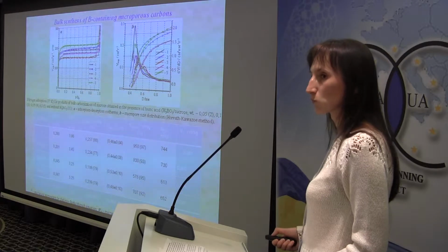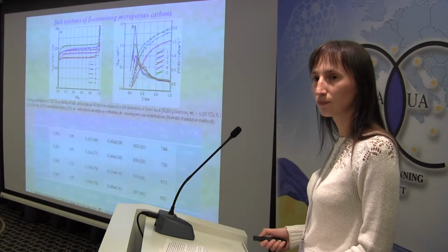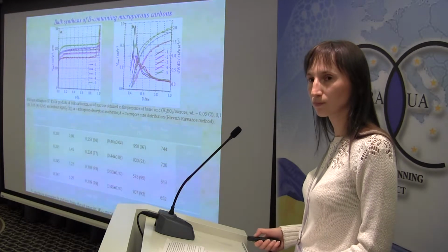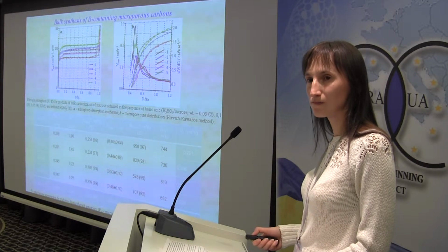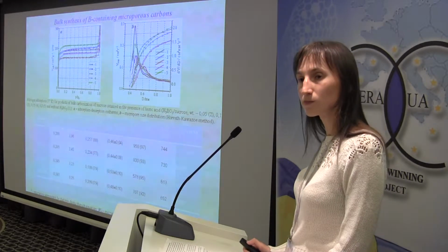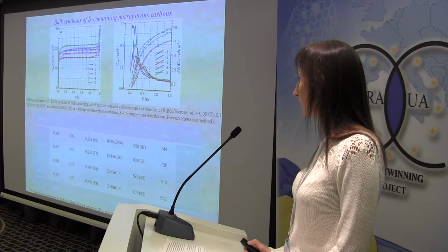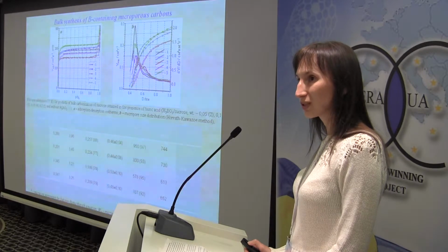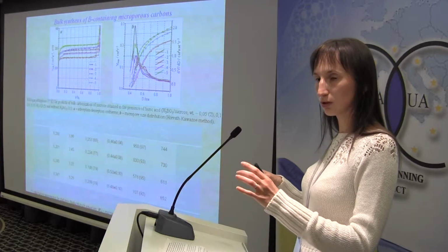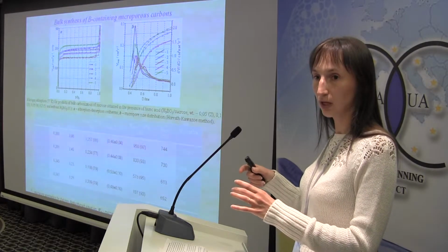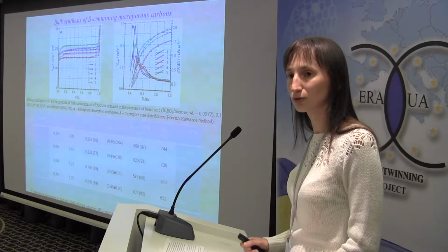Other questions, please? Yes, please. It is well known that boron atoms as well as nitrogen atoms are very popular impurity atoms for substitution in two-dimensional carbon. In your boron-containing nanoporous material, what is the concentration of these atoms and what is their configuration? Do they substitute atoms? And are they random or maybe correlated? The concentration of boron atoms is from 1 to 1.5 weight percent. From the literature, it is known that there is incorporated boron and boron on the surface. So there is a boron-carbon bond and a boron-oxygen bond on the surface. And now we wait for results of X-ray photoelectron spectroscopy to know exactly the fraction of those boron.